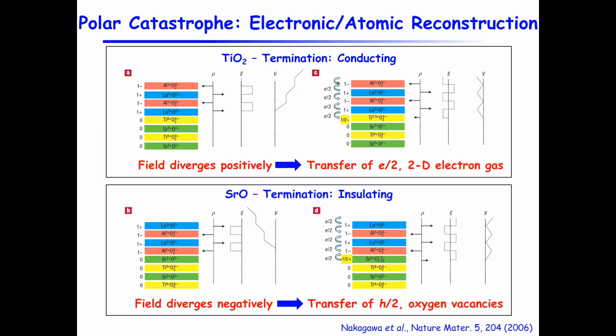So if we look at this again, if we grow lanthanum aluminate on strontium titanate, then we have a problem that in the lanthanum aluminate layer, there will be an electric field that would diverge. Right? If it is on a titanium dioxide terminated layer, it diverges positively. If it's a strontium oxide layer, it diverges negatively. So to deal with this, for the titanium dioxide termination case, you would transfer half of an electron to the interface. That's proposed to be the origin of this 2D electron gas system.